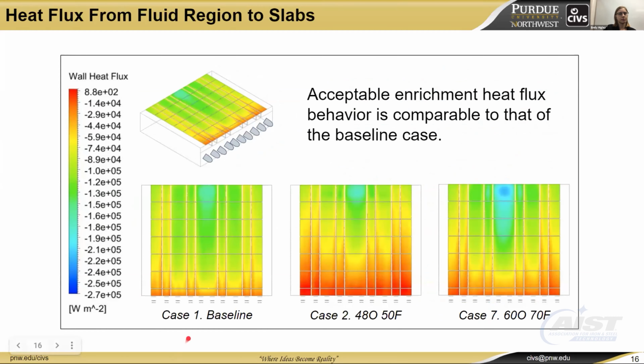So this slide shows a comparison between the heat flux leaving the fluid region and entering the bottoms of the slabs for the baseline and the two optimal enrichment cases. The main thing to note about this slide is that these were the enrichment cases that were found to be optimally comparable within their categories to the baseline heat flux. And as John stated earlier, this is important because uneven heating can cause uneven temperatures of slabs, uneven properties, and damage can occur when slabs are further processed. So this is very important.